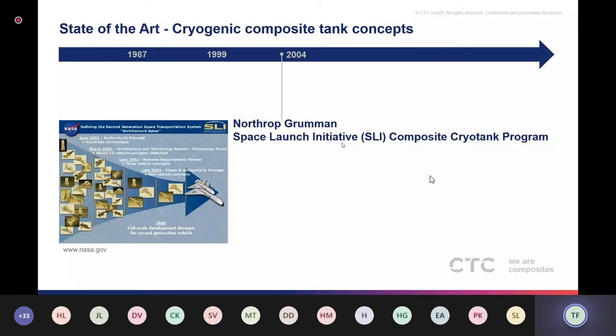40 filling cycles also indicates one major difference between aircraft tanks and space tanks, because while for space 40 filling and draining cycles with liquid hydrogen are perfectly enough, for an aircraft this is of course way below the number that is required. Thousands of filling cycles have to be endured by the tank, which has to be considered in aircraft CFRP tanks.